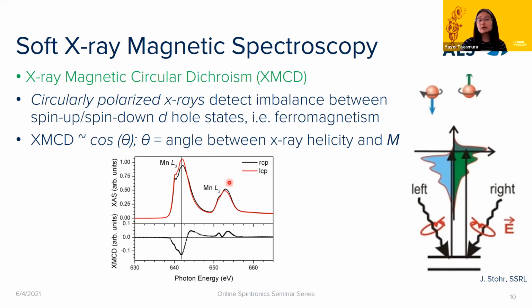And then we can also do things like take hysteresis loops, because the intensity of this XMCD has a cosine theta dependence, where theta is the angle between the X-ray helicity and the magnetization. So we'll be able to use that fact when we actually look at some of the images of magnetic domains.